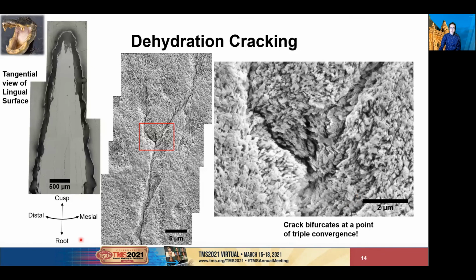Rotating our perspective to look at the lingual surface head-on, we're now looking at one of those long root-to-cusp cracks. This crack can be seen to bifurcate at a point of triple convergence. On each side of the crack, you can see the nanocrystals kind of leaning in towards each other, meaning that this must be an intersection of 3 adjacent columns.